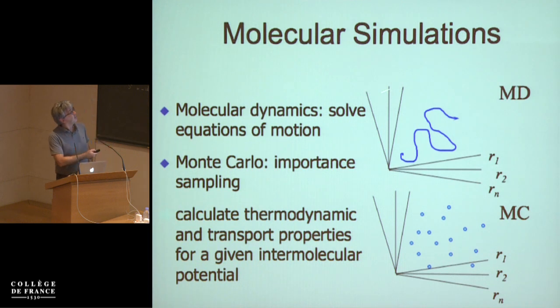And what we do there is we basically use a force field. We try to estimate the interactions of these gas molecules with the frameworks, to try to, well, basically we make a flight simulator for molecules. So if you simulate sufficiently long the movement of these molecules in the pores, you can predict thermodynamic properties. And we'll see some examples. So the recipe is, we make the crystal, we optimize the crystal using quantum chemistry, and then we use these molecular simulation techniques to predict experimentally measurable properties of these materials. And that should be sufficient to make predictions on the performance.